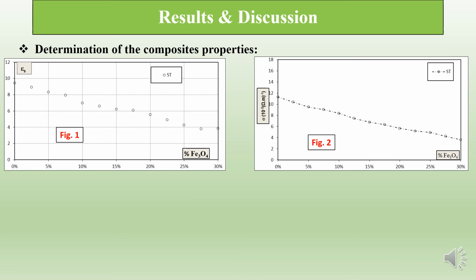Figure 2 shows the static conductivity profile as a function of the iron oxide volume fractions for a frequency value of 200 MHz, which is maintained constant. From the graphical examination of the results obtained, a visible decay of the static conductivity can be noted when the volume fraction of the iron oxide increases.